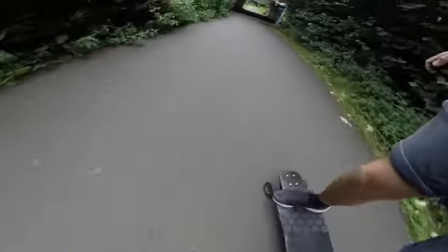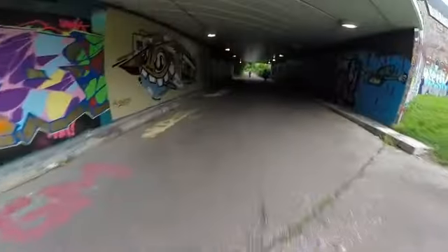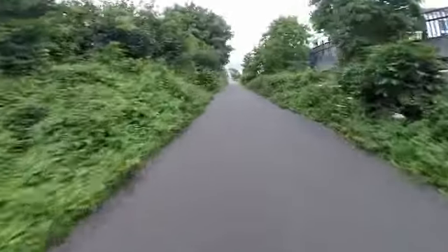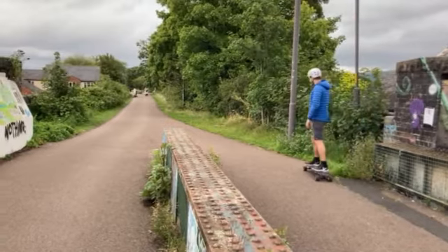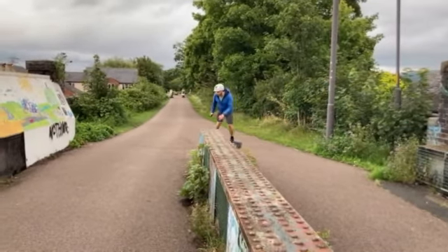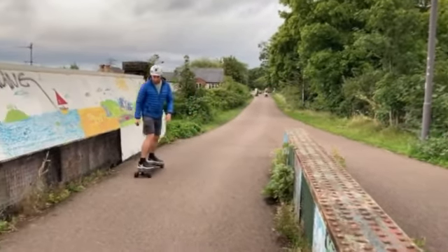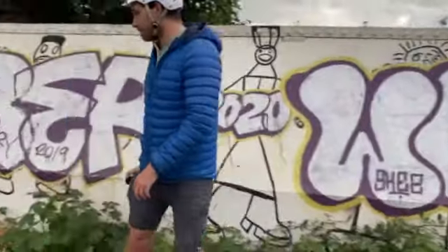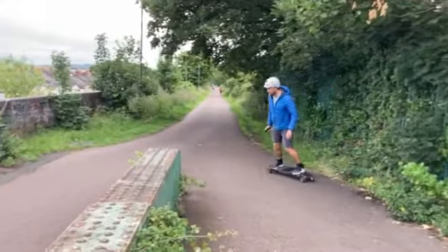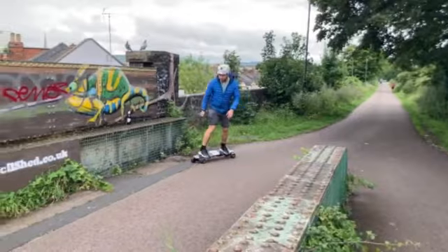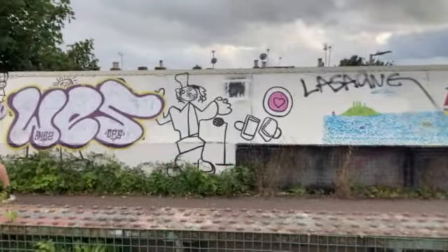The first test was performed with repeated heavy acceleration up to its top speed and sharp deceleration, achieving a range of 8 miles. The second test was repeated along the same test track but travelling at a slower, smoother, steady speed of 10 to 15 miles an hour. From the second test, I recorded a range of 12 miles. The range had increased by 50% with a steady and smooth riding style, highlighting the inefficiencies associated with accelerating a mass up to speed repeatedly.